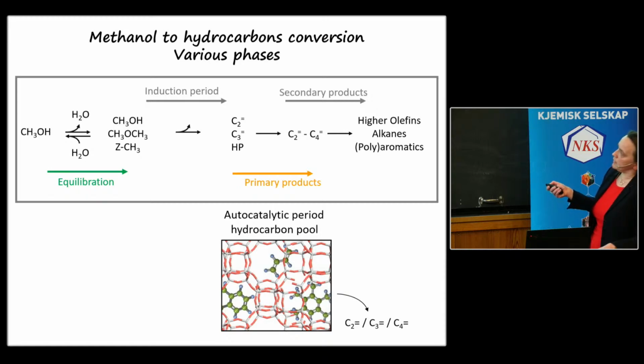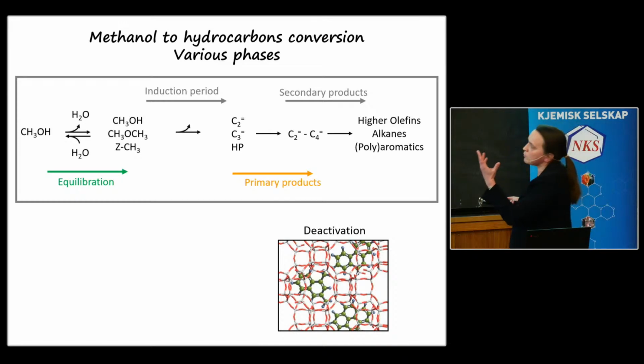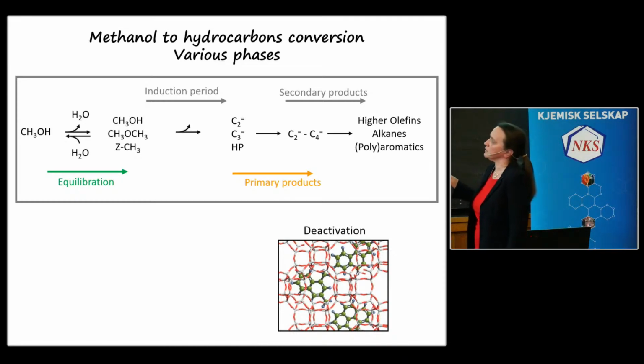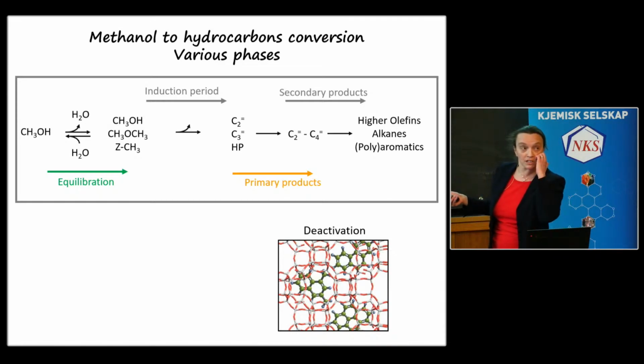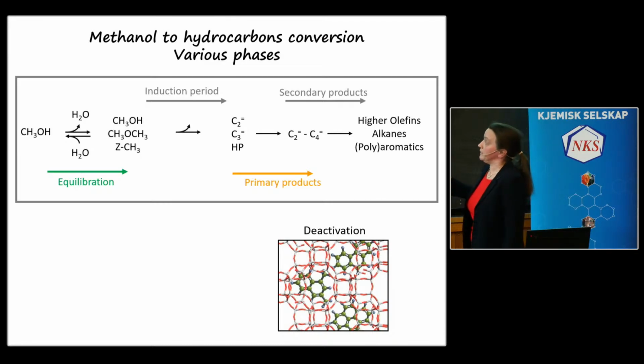And the real active catalyst, we can see that hydrocarbon pool species are embedded into the zeolite. And basically, this is the catalyst that we want. So we also need the Brønsted acidic proton, but we also need these other components. Otherwise, we do not have the active catalyst. So you can see it's a very complex catalyst. Yeah? And of course, with time on stream, the catalyst can also deactivate. So remember my mountains with the rocks that came down. So basically, here you can compare that to a deactivated catalyst. So here, these hydrocarbon pool species have aged and they block everything.